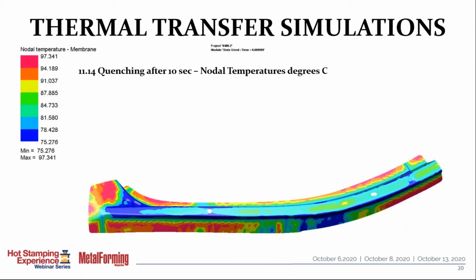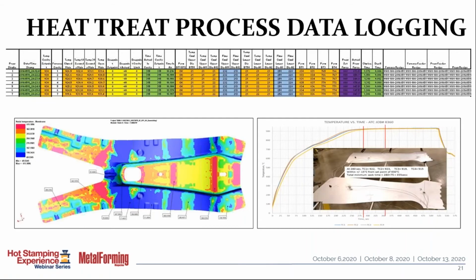So here you can see we're at very good temperatures after 10 seconds. This particular part didn't need to quench any faster than 10 seconds because the press that it was going into was very slow. And so this was a very acceptable simulation. And we found when we built the tool that that's exactly what happened.